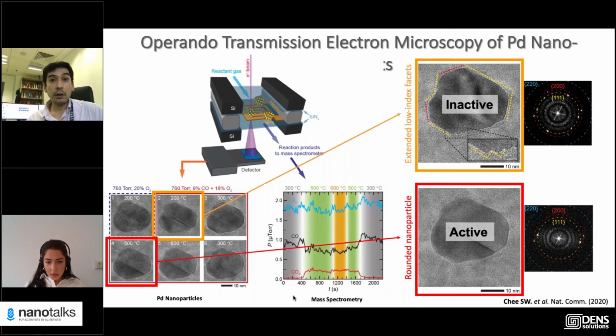So right now, what we're trying to do is develop the imaging method so that we can use a very low dose, but at the same time still get meaningful data. So far, my postdoc tried with ceria, and we can really see that when we heat it up under atmospheric pressure, you start slowly chewing up the material. So the next thing is really figuring out how to image it without damaging the support, because to be able to tell anything about the support, you really need to go to high resolution, and that requires quite high doses. I completely agree with you, and I share your skepticism, but I think it's not that far away.